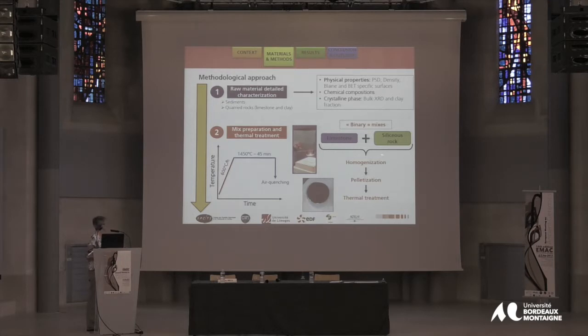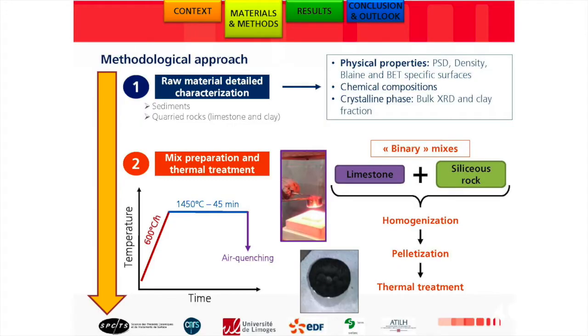Then these are homogenized, pelletized into small beads, and heat treated: a ramp of 600 Celsius per hour, 1450 dwell temperature for 45 minutes. These conditions are very close to what is done in a cement plant, followed by air quenching. After air quenching, we obtain these beads, which are crushed to give the cement.